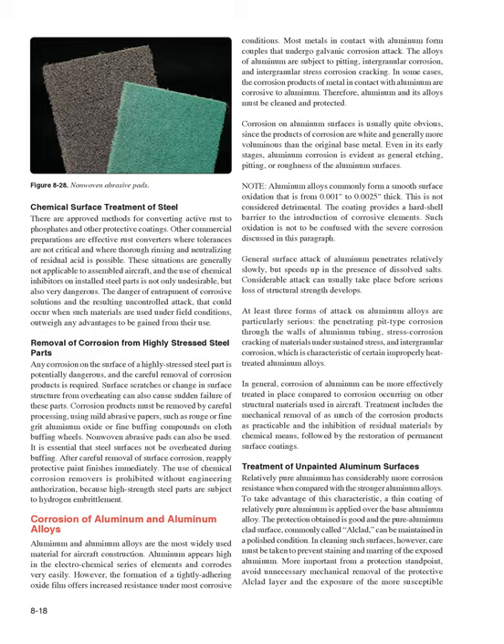Corrosion on aluminum surfaces is usually quite obvious, since the products of corrosion are white and generally more voluminous than the original base metal. Even in its early stages, aluminum corrosion is evident as general etching, pitting, or roughness of the aluminum surfaces. Note, aluminum alloys commonly form a smooth surface oxidation that is from 0.001 inches to 0.0025 inches thick. This is not considered detrimental. The coating provides a hard shell barrier to the introduction of corrosive elements. Such oxidation is not to be confused with the severe corrosion discussed in this paragraph.